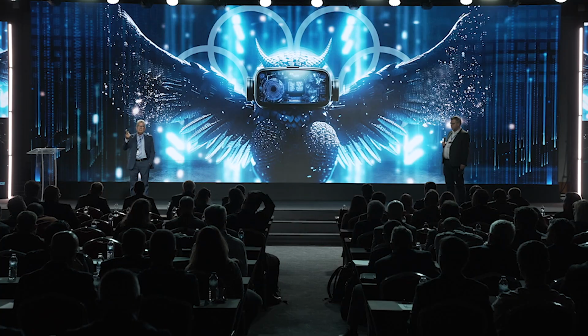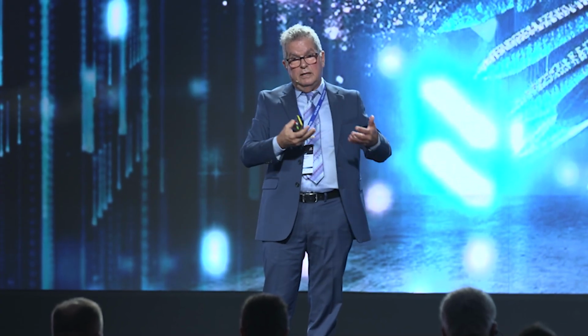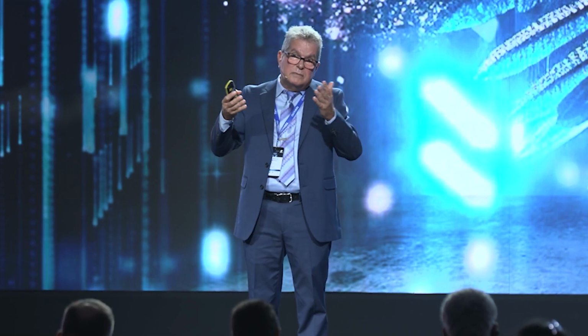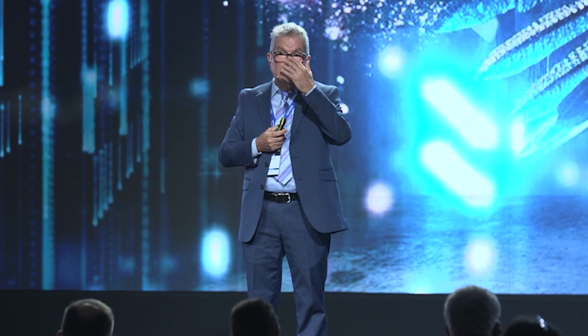The problem with the flash is that normally you have less than 400 kilocalories per kilogram, but then you have to dry the material before you feed the material to the system. And in drying the material, you spend 120, 130 kilocalories per kilogram of material, and then it goes up to 500 or something. Whereas in the rotary, it also depends on the type of rotary. The newest design is a double body, where you have a dryer and a calciner, and there you can get 520 kilocalories per kilogram. I mean, it depends on each case. But yes, it's also an interesting point.